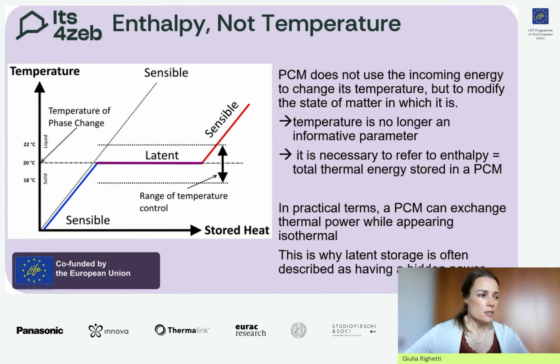So this brings us to a key conceptual shift. When working with latent storages, temperature is no longer the most informative variable. We have to introduce another one, enthalpy. Because during melting and solidification, PCM doesn't use the energy to change its temperature, but energy is used to change the state of the matter from solid to liquid and vice versa. As a consequence, temperature remains almost constant while a lot of energy is exchanged.